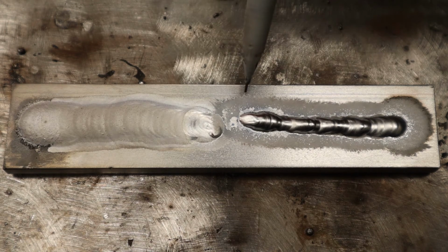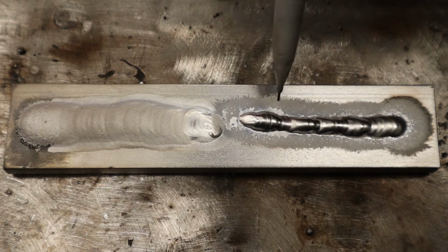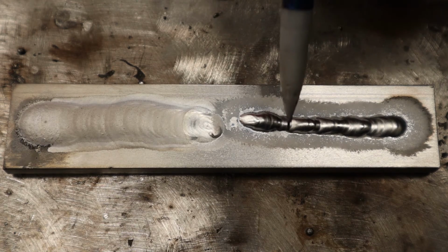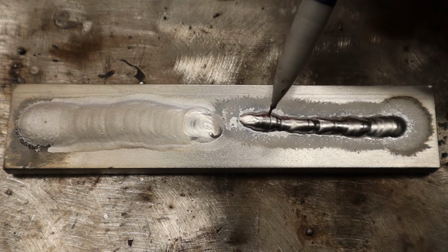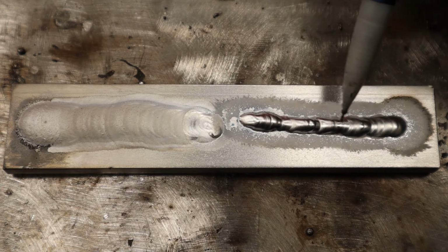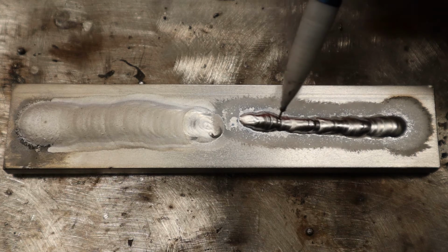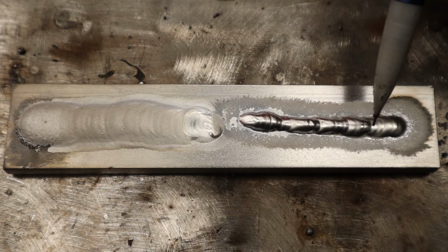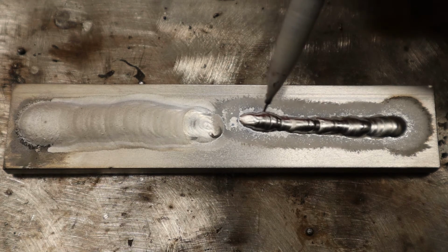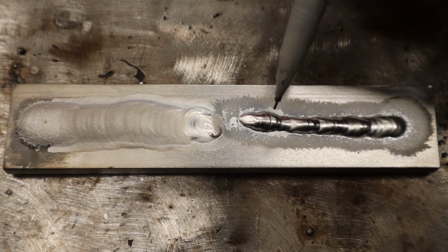It's actually the same width. However, it's more obvious because we have this little weld bead that looks like a little worm from it being too cold. Now, first thing you'll notice, it's a little bit shinier, right? So you do tend to get cleaner welds with lesser temperatures. So you kind of have to use this as a gauge too, if you're wanting these shinier looking welds, then you got to watch your heat.